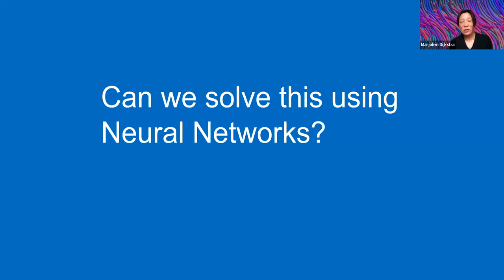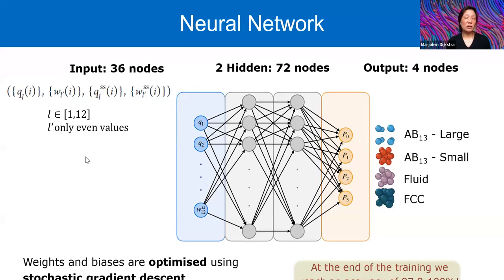So the question that we ask ourselves is, can we solve these complications by using a neural network? What we did is calculate all these bond order parameters, the quadratic and the cubic ones. We also separated the different species. In total, we had 36 local descriptors for every particle. By training a neural network with configurations that we already know from the AB13 crystal structure, the fluid, and the FCC phase, we were able to train the neural network in such a way that it can identify these different